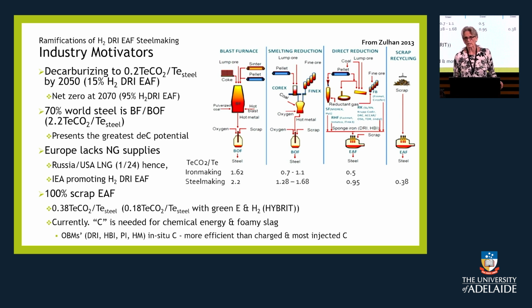The Europeans, with the potentially lack of natural gas, have pushed for the Hydrogen-DRI process for them moving forward. The IEA is promoting various percentages as we move to 2070, as you will see. But the 100% scrap is actually rated at 0.38 tons of CO2 as it stands currently. And if you increase the amount of renewable energy going to an EAF, that will drop significantly. And with Hydrogen-DRI EAF, it will drop to 0.18. 100% scrap EAF is challenged moving forward because of the availability of good, clean scrap.